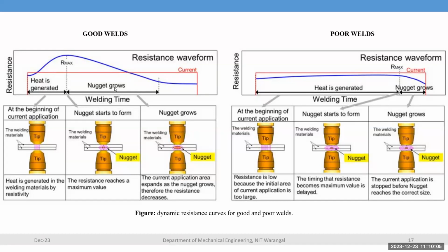This period is nugget growth, and this period is heat generation. At the beginning of the current application, the nugget starts from this portion, and the nugget grows, and based on this you get this kind of curve. So once the curve is like this, you can say that this weld is a very good one without any defects. Now this second portion, the poor welds, you can see the R maximum is somewhere else, because more heat is generated than required. That's why expulsion of the welds takes place. So that leads to defective welds.